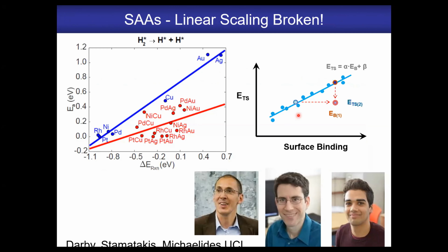weak binding. And more recently, a group led by Mikhail Stamatakis at University College London has computed Brønsted and Polanyi plots for the pure metals for hydrogen dissociation, as seen here in blue, and then for a lot of single atom alloys seen here in red. And what you can see is that there's no real linear scaling anymore. There's a big cluster of points here. But most excitingly, it lies on the underside of the curve, which means for all these combinations, we should have a faster rate of dissociation of molecular hydrogen while keeping the weak binding of the hydrogen on the surface.